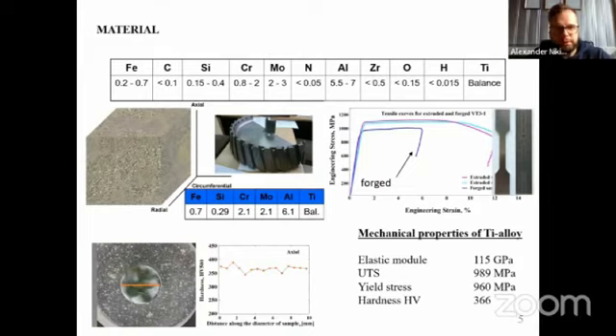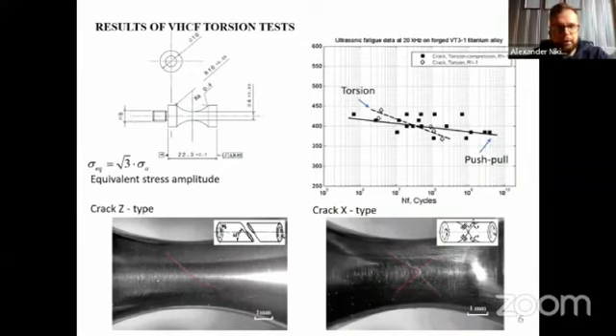It's very interesting to test this material because it has no non-metallic inclusions. For example, the first results for steels show that sometimes we have subsurface crack initiation at an inclusion. Here, in the case of the titanium alloy, we don't have an inclusion and still have different types of crack. Here I present briefly the results of the experimental tests on this material. On the right, you have a push-pull test on the same titanium alloy. It's an axial test, and we use the equivalent stress to compare with the results of the torsional test. You see torsional and axial results match each other pretty well.